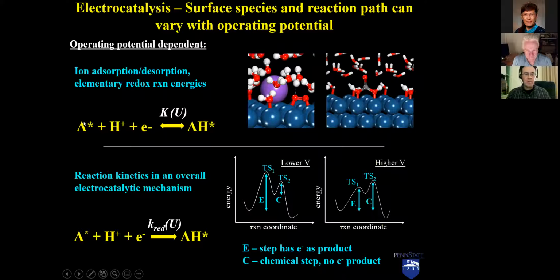And I said we can absorb to a surface, but if instead of a bare surface, a star being what we're absorbing to, we absorb to a surface that has a species on it. So for instance, carbon dioxide, then this would be converting carbon dioxide plus protons plus electrons to, say, COOH, an intermediate in that CO2 reduction. And the same type of approach is going to occur there, where instead of starting with a surface with nothing on it, we start with a surface with CO2, and we want to know the rate at which it transfers electrons in elementary steps to get rates and rate constants to predict reaction.